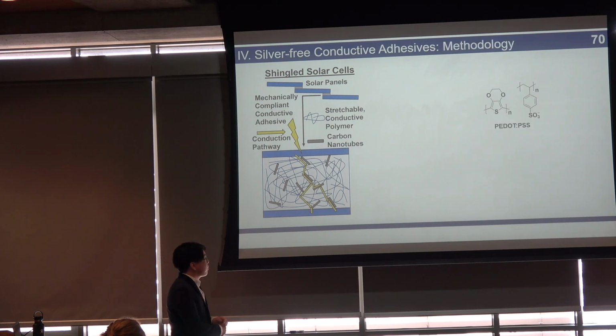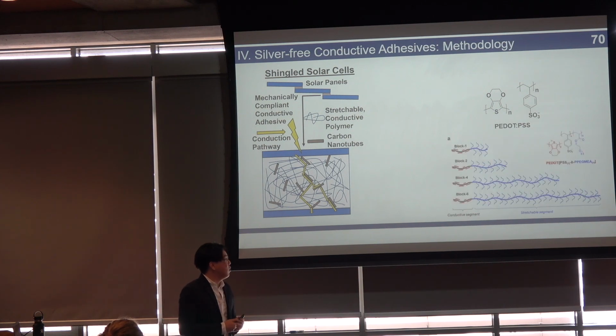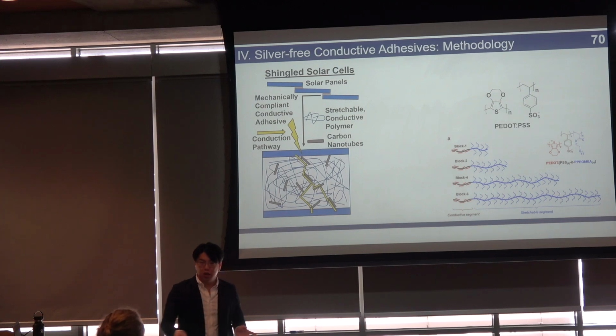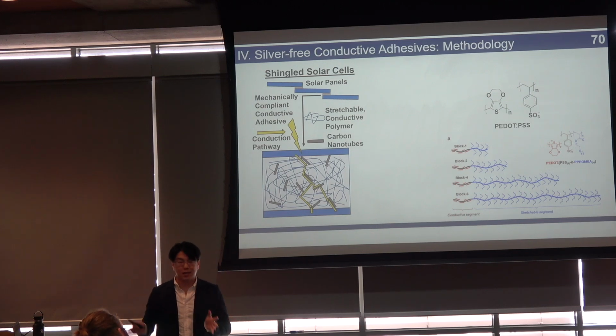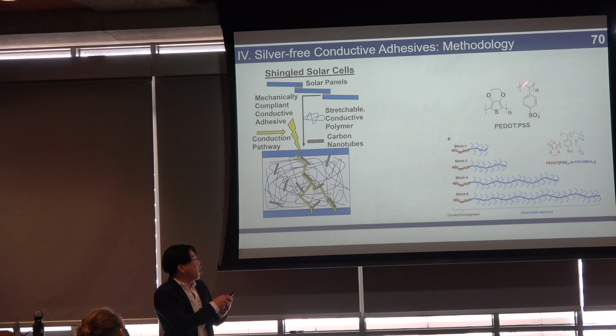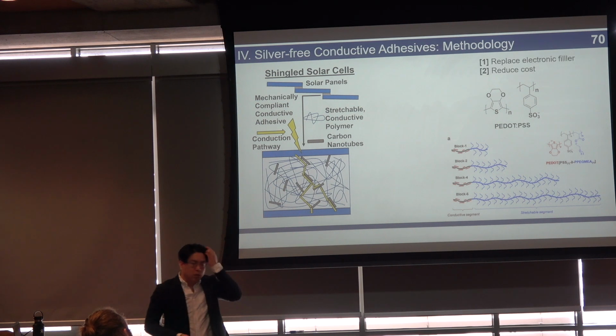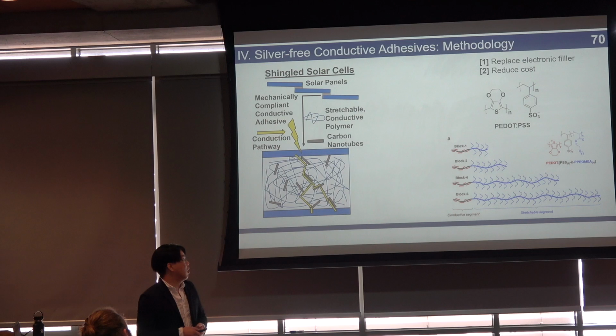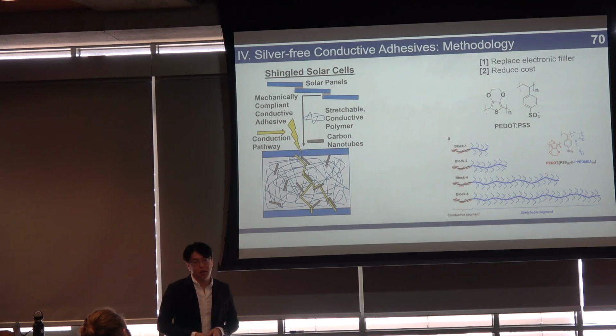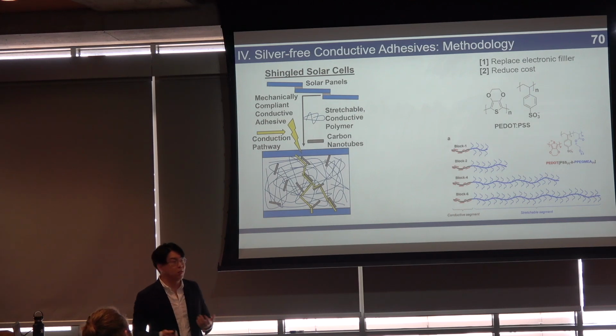So we're working with a conductive polymer called PEDOT:PSS, and previous work from our group has shown that you can actually modulate the mechanical properties of these conducting polymers by copolymerizing this PSS block with a long and soft side chain. Our two central goals here are, of course, to replace or reduce the electronic filler, and also to reduce the cost. So we can immediately see how we're doing with number 2.